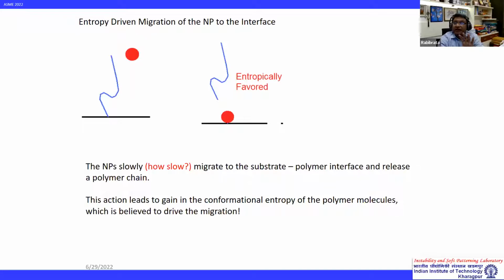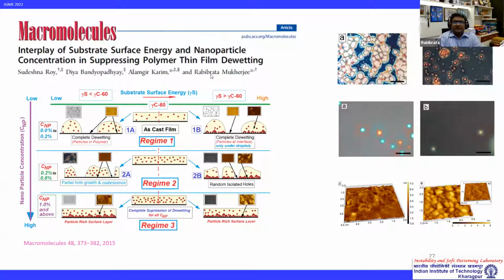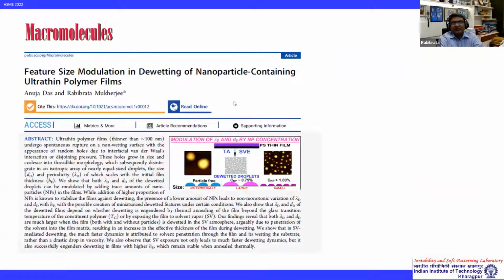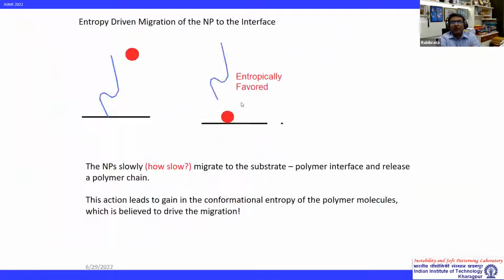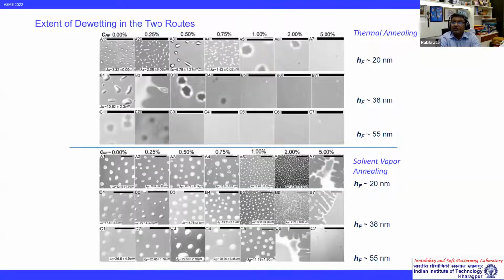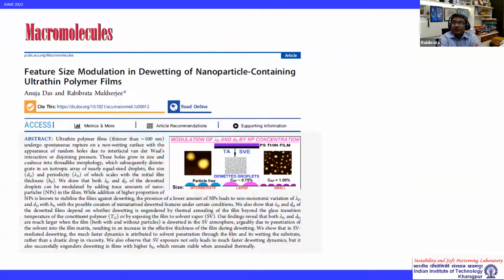For a long time, there was no direct evidence. Microscopically, you see that the film remains stable, but what exactly was happening to these nanoparticles, nobody knew. So we also started to look into this system for a while, and we looked into the different effects of the surface energy of the substrate and the filler particles, how they influence, and we came up with some regime maps, et cetera. This is also a recent work which I was talking about, where we showed the difference between nanoparticle-containing films, and how the dewetting mechanism differs if it is done by thermal annealing versus solvent vapor exposure.